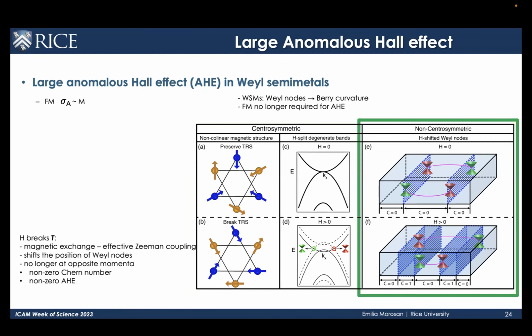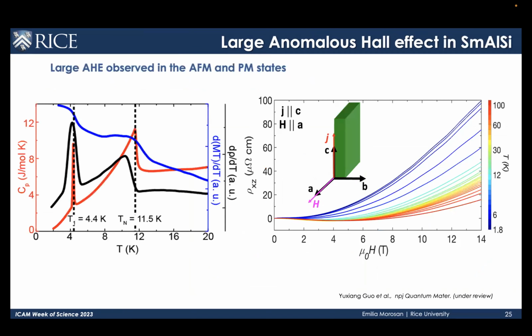So here's what we observe in samarium aluminum silicon. This is just a summary of the low temperature data, which includes the black curve, a derivative of resistivity, the red curve, specific heat, and the blue, a derivative of magnetization, all pointing to the magnetic order below 11.5 Kelvin, and then a spin reorientation to the lower temperature.